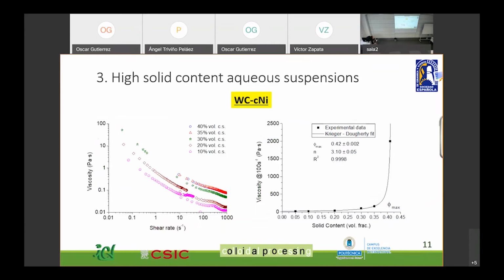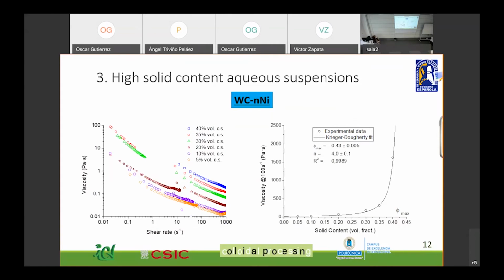After the milling step, we decided also to carry out some rheological tests, but in this case, to determine the optimal amount of solid content for our suspensions. We did this experiment for the mixture of tungsten carbide and commercial nickel, and we did the same for tungsten carbide and nano nickel. In both cases, we could determine there is 40% in volume, which would be our optimal solid content. And from that point, again, we see the viscosity of the suspension increased too much.